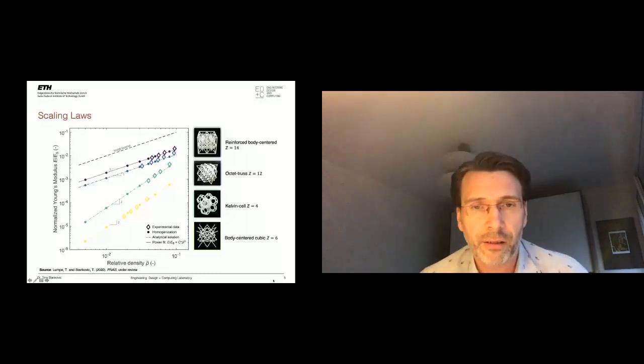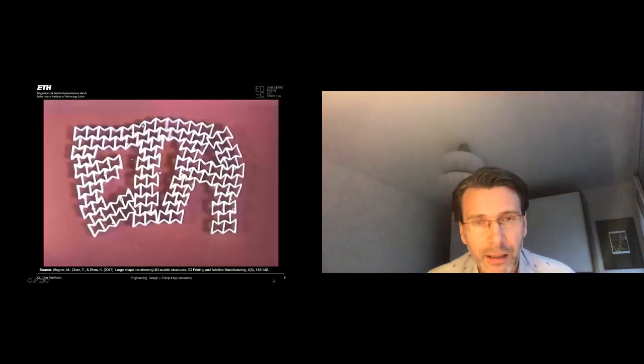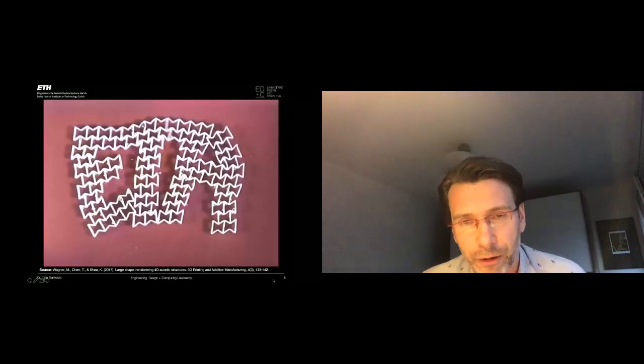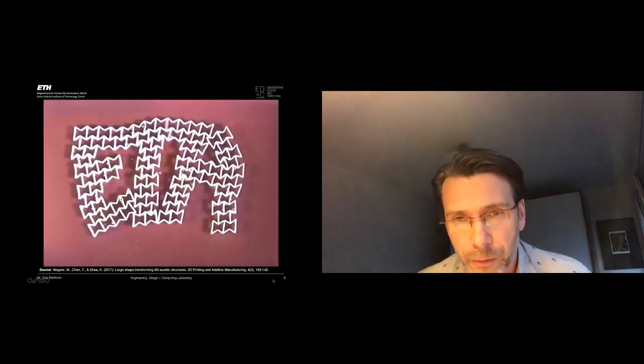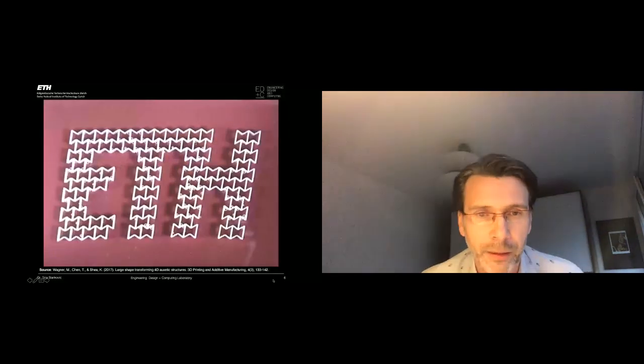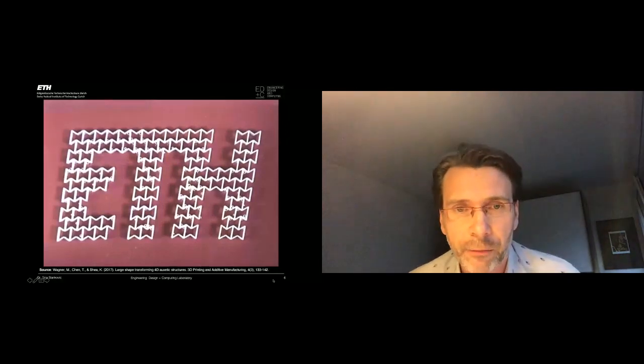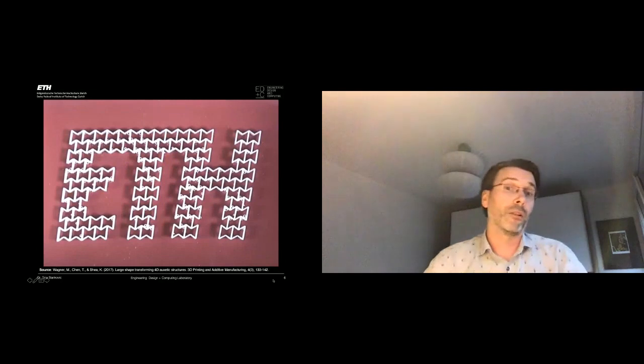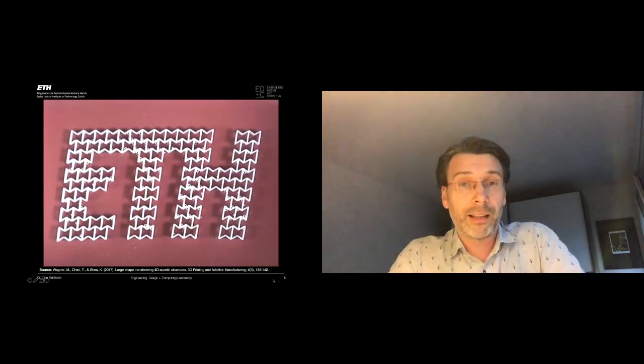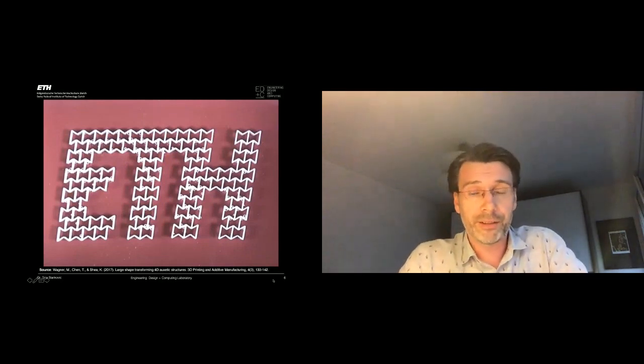That allows us for further applications. For instance, here I show this movie often, our ETH logo being 4D printed and then trained with shape memory polymers to develop. This is, of course, an auxetic structure, which allows us to have a negative Poisson's ratio. It also allows us to achieve significantly large displacements, which was necessary for this example.